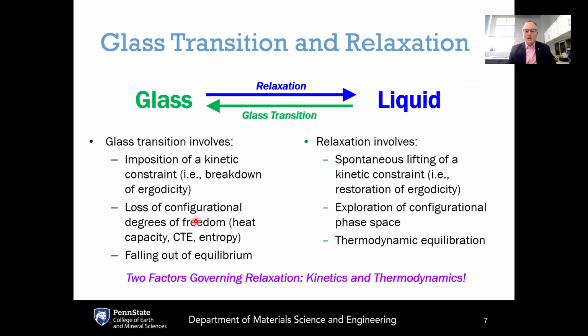And therefore, all the configurational contributions to properties end up being lost. So there is a decrease of the heat capacity in going from the liquid to the glass because of that loss of configurational degrees of freedom. There's a decrease in the thermal expansion coefficient, and a decrease of the entropy, because we are no longer able to freely explore all these different configurations. And this is what causes a falling out of equilibrium of the system. So this is the glass transition. It is a conversion from an ergodic liquid to a non-ergodic glass.